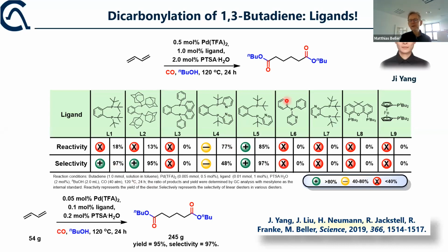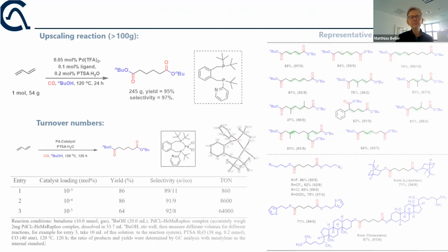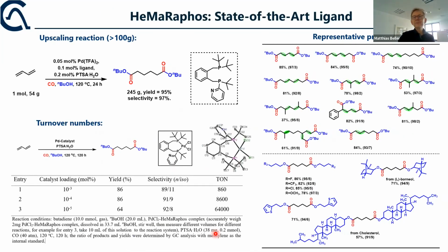It still has high reactivity, similar, I would say, to the previous ligand, but it also has very nice selectivity like the Lucite ligand. And with this ligand, you can see we did in our laboratories 1 liter, 2 liter scale type reactions, and we are now building at the moment in our laboratories a small continuous plant for doing this reaction on a larger scale. The turnover numbers, I just want to highlight this, also can go up to several 10,000. We are still working on improvement. You can use many other 1,3-dienes in this type of chemistry, which might be also interesting for synthesis.